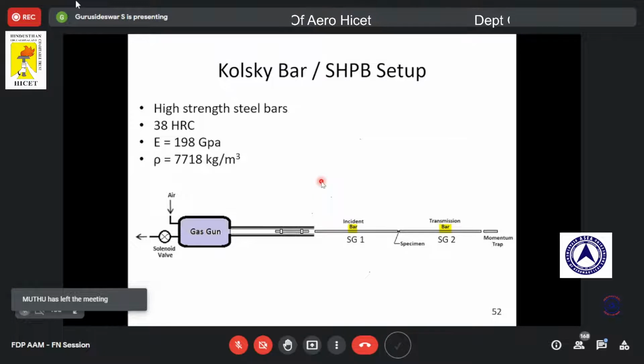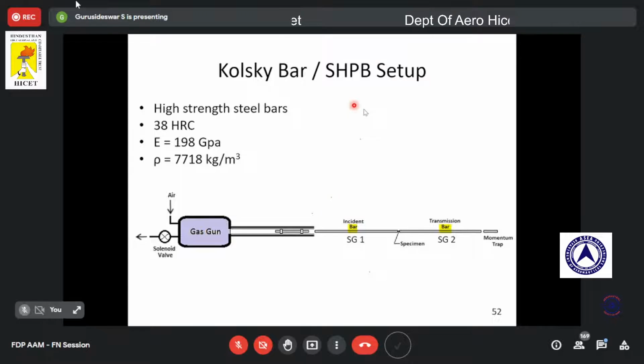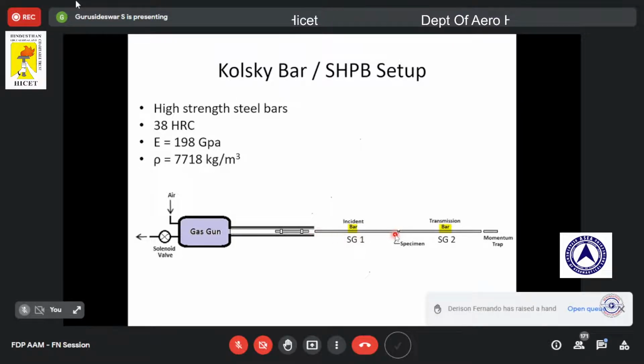Anyway, as I was telling in my previous slides, we use Kolsky bar to achieve very high strain rates. So this is the typical representation of a split Hopkinson pressure bar. It works on one-dimensional wave propagation. I have given the schematic of that pressure bar setup. Here, when the striker bar hits the incident bar, a stress wave will be generated. This stress wave will propagate through this incident bar.